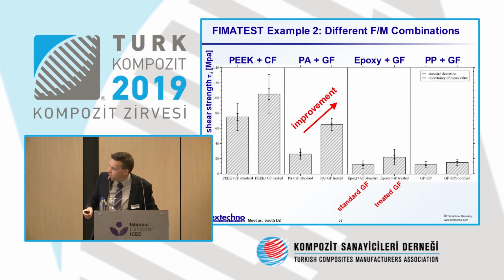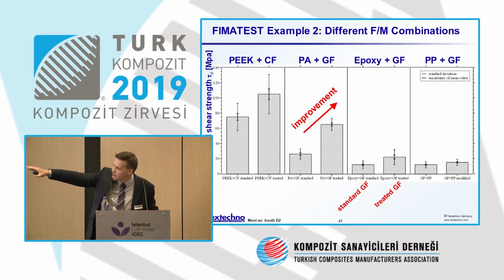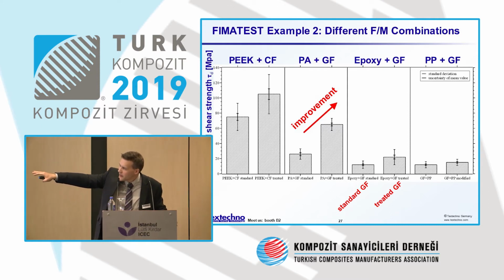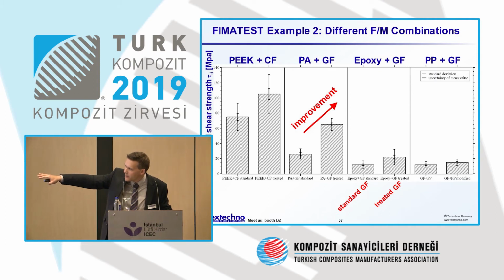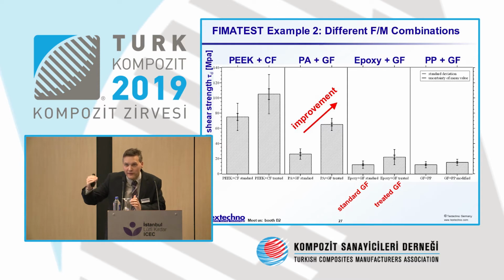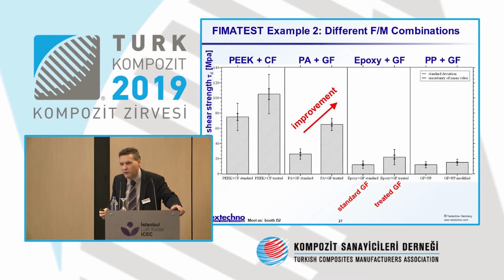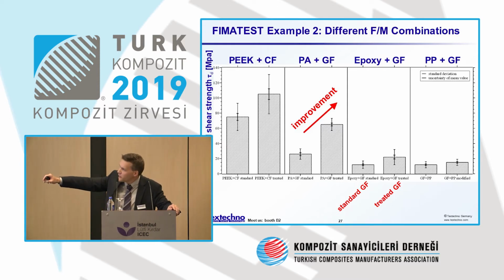Maybe a few more examples are given here. We've got a carbon fiber embedded in PEEK. On the left-hand side, you see that there was a standard carbon fiber and a treated carbon fiber, and it made a huge difference in the local interfacial shear strength that we are assessing. The second example is a glass fiber and polyamide. Then there is a glass fiber and epoxy, and a glass fiber and PP. So actually we haven't come across any combination of fiber and matrix that we weren't able to measure.